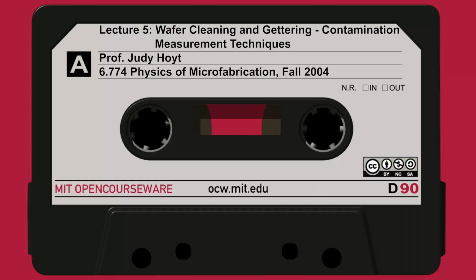Now, at high enough temperatures, say if you put it in the furnace to oxidize above 1,000 or anneal it, the oxide can relieve some of the stress by viscous flow. But that's only at a high enough temperature where the glass starts to soften a little bit. At lower temperatures, it's just too viscous to flow, so the stress stays built in. So there are these intrinsic stresses just because of the volume expansion. There are also differences in the thermal expansion coefficients of SiO2 and silicon, and that leads to a certain amount of intrinsic stress.